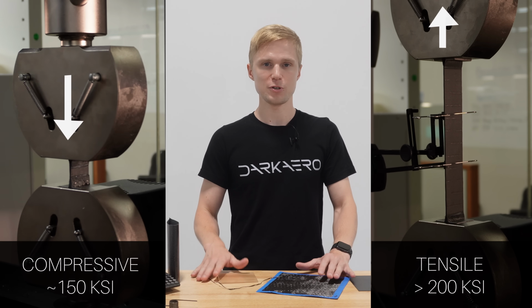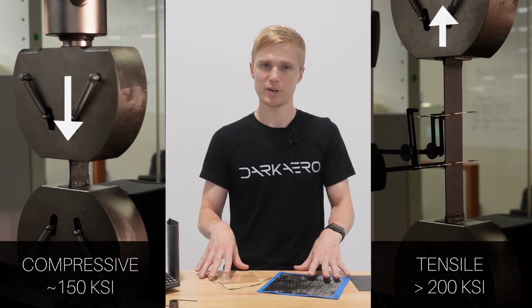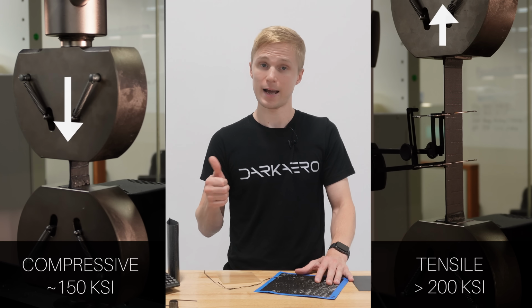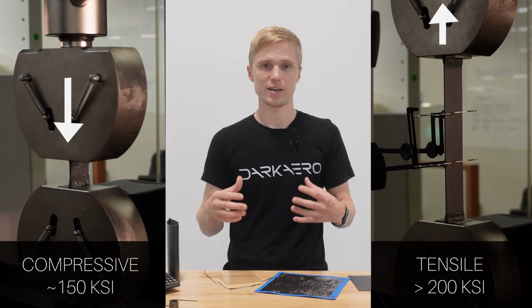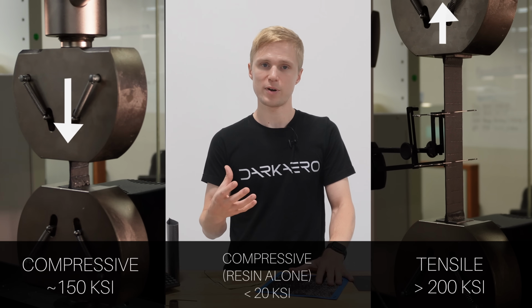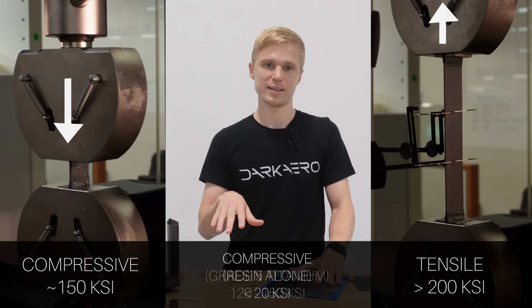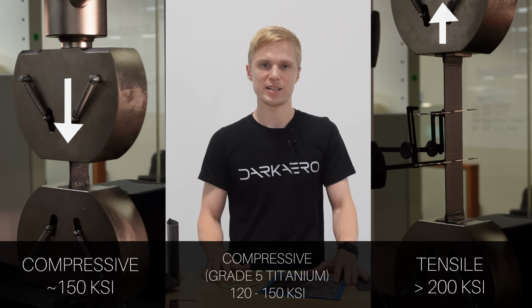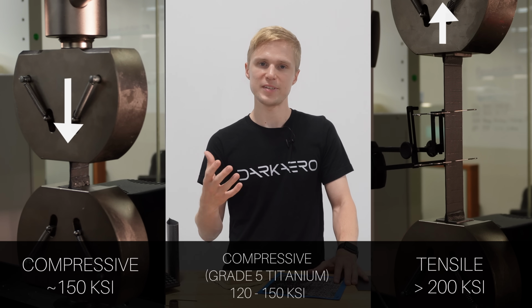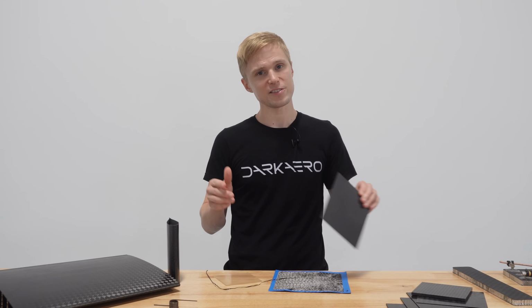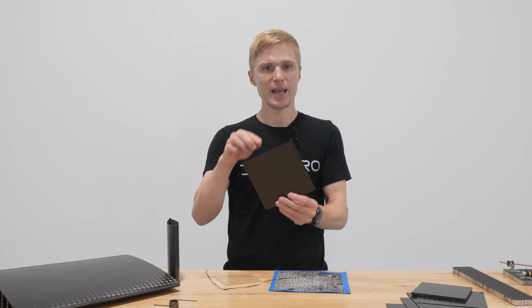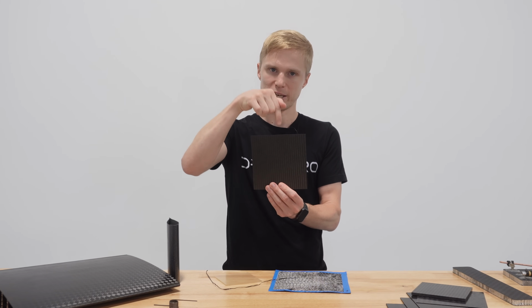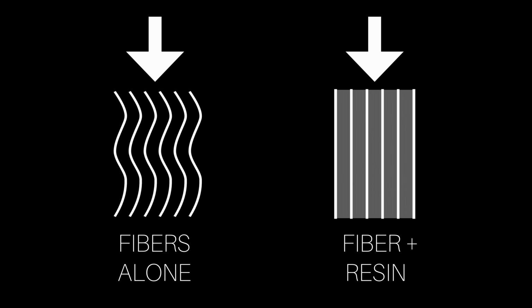The tensile strength of unidirectional carbon fiber composite loaded in the fiber direction can easily reach values of 200 KSI and higher. Compressive strength values of 150 KSI are attainable for the same material, while the compressive strength of the resin alone is rarely over 20 KSI. For comparison, the compressive strength of grade 5 titanium is around 120 to 150 KSI. Within acceptable temperature limits, the strength of a carbon fiber composite is mainly determined by the amount of fiber in the composite and the orientation of the fibers relative to the applied load. Carbon fiber composite can support compressive loads because the resin matrix stabilizes the reinforcement fibers, allowing them to hold their shape and resist compressive loads.